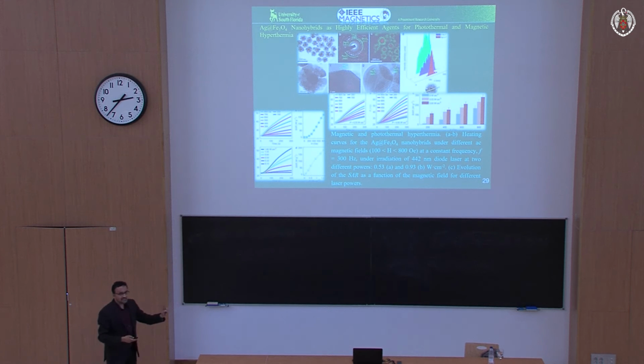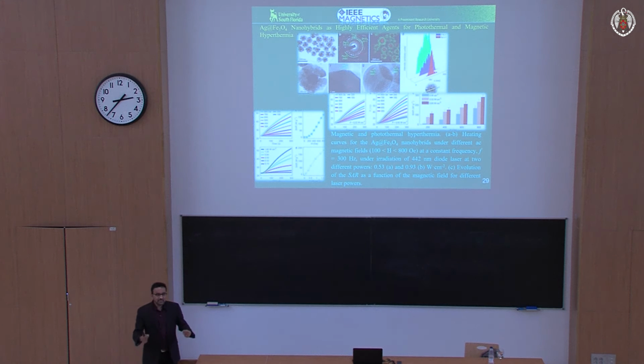The other thing is, AC magnetic hyperthermia is not the only way to generate heat. You can actually generate it with metallic particles. In, let's say, 10 nanometer gold particles, if you excite them with a laser at the right frequency, you can excite the surface plasmon resonance, and also you can have dissipation. So you can generate heat with metallic particles.